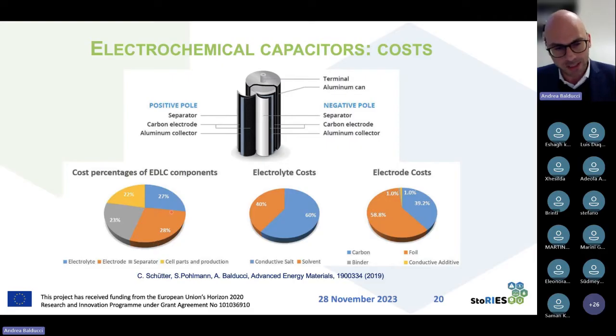The electrode is 28%, and then there is a larger share of cost given by the separator, which is more than 20%, and the cell part and production, which again account for more than 20%. If we go a bit more in detail about the electrolyte, its cost is divided between 60% conductive salt and 40% solvent, the acetonitrile we were discussing before. In the case of the electrode, the carbon is something like 39%, the binder accounts for 1%, like the conductive additive, and what costs a lot is actually the current collector.